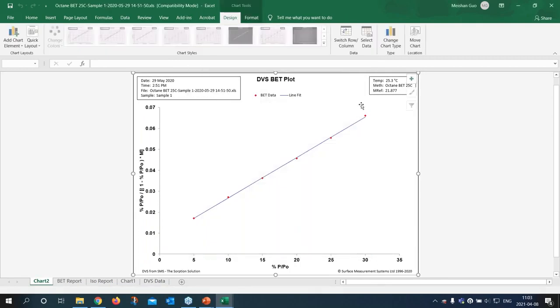And by plotting the line, it will give you the BET lines for this sample. And if you see any of the points is beyond this line, for example, one point is here, in that case, you can go back to the original panel and exclude this point from the calculation. So basically, all the calculation is rather simple with the analysis software.